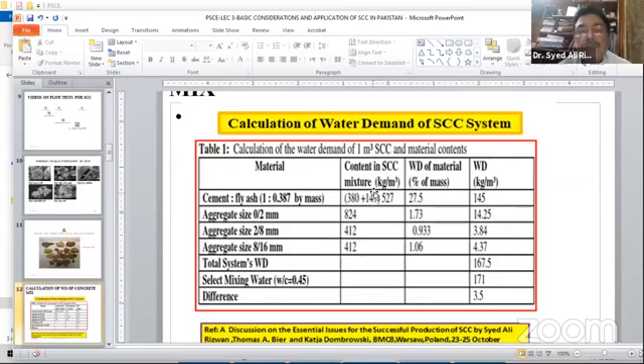The powder content in SCC will be 380 plus 147. If cement is 380, then this will be 380 into 0.387, 147. So the total is 527. You can determine the water demand; if it comes out to be 27.5%, you multiply this with that, you get 145 kg per meter cube. So you can see a lot of water demand by the powders. Then I determine the water demands of the aggregate sizes according to ASTM standards. You can add them together, and the total water demand of the system was 167.5. So I chose a water cement ratio of 0.45, which gives us a water of 171 kg per meter cube.